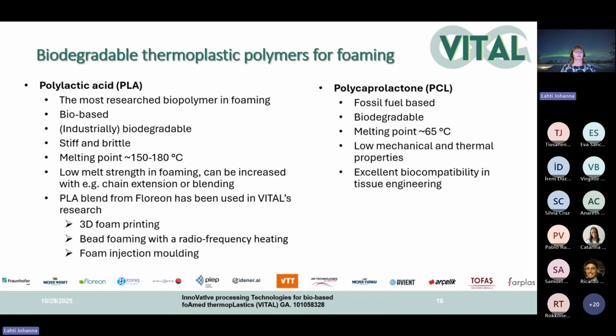And as we know, it is a bio-based polymer, and it is industrially biodegradable. It has some challenges, or some typical properties. So it is very stiff, it can be brittle. So these can be challenges in some cases. Melting point you see there. Some challenges with melt strength sometimes in foaming, and this can be affected, for example, with blending with some other polymer or by using chain extenders. And in the Vital project, we have been studying, for example, a PLA blend from Floreon in these different foaming processes which we are using in this project. So in 3D foam printing, in bead foaming, and in foam injection molding. Maybe you will hear about that later on.